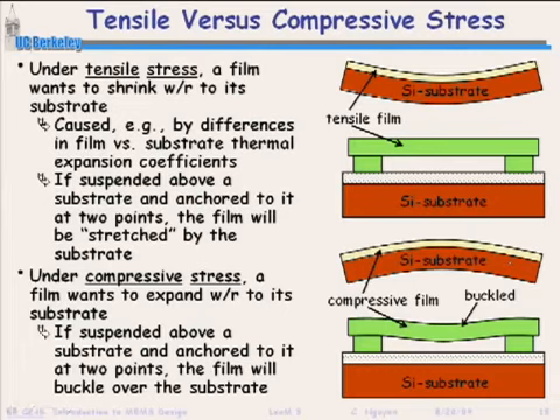So if this film is suspended on the substrate, these are anchors to the substrate. Think of anchors as points that cannot move. The substrate is much bigger than the structure, so it's holding those anchors in place. But this film wants to grow in the lateral direction. It's not going to be able to grow laterally unless it buckles like this. This is called buckling, where you have two anchors holding its ends in place. The film wants to stretch laterally, and the only way it could do that is to bend. And that's a problem, especially if it buckles so much that it touches the substrate. Now you've got friction against moving, and you have a very hard time moving this thing. So both of these stresses are important to control.